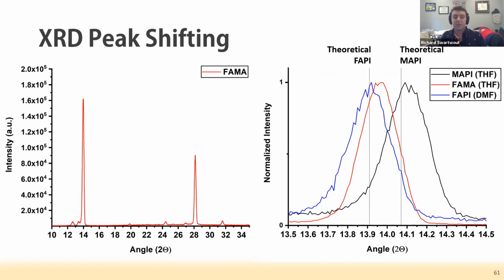If we look at the theoretical peaks, the formamidinium lead iodide corresponds pretty strongly with where the theoretical unit cell peak should be.